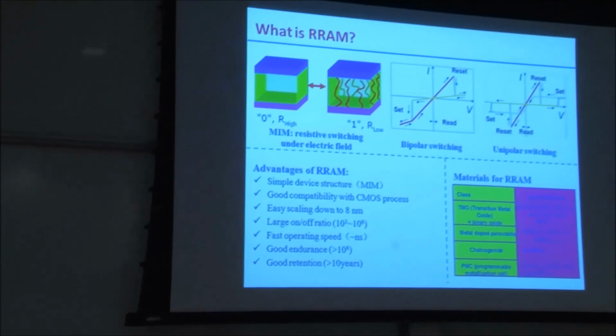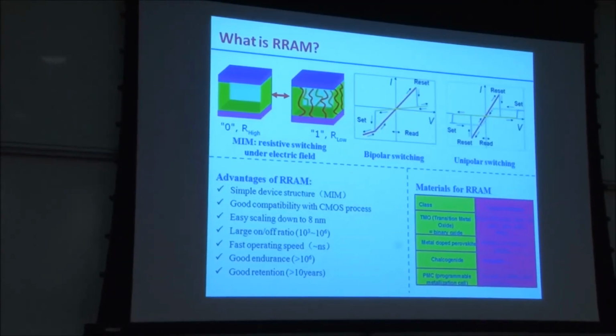Yeah, actually, this is a good question. So we can see these cartoons. Usually in the RRAM, both electrodes are metal. The switching layer is an insulating layer. Usually they are not conductive. But is it that you always mention high K material? Not only high K, a lot of even polymers, even some like PCMO, a lot of materials have this performance. But you're using the inorganic zirconium oxide as a model? Yeah, actually, because this material may be easier to realize commercial application.